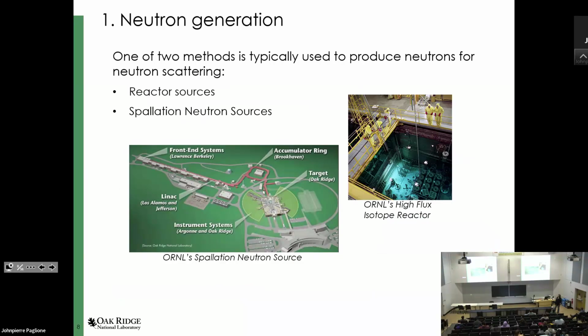So just a brief overview, neutrons are usually generated by two methods for high pressure neutron scattering or any sort of scattering experiments. They're either made in a typical neutron reactor. So in Oak Ridge, we have the High Flux Isotope Reactor, which we use for these purposes. Or they're made by a spallation neutron source, where you accelerate some protons, essentially, and you hit a target that then spalls out the neutrons. Both these processes are not as efficient as the photon generation at a synchrotron. So as a result, our flux is a lot lower, and that really drives a lot of the development and the things we do.